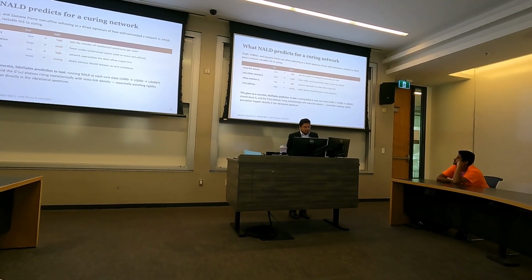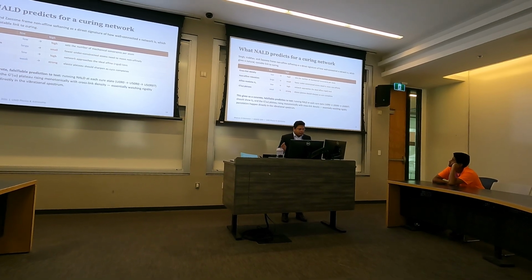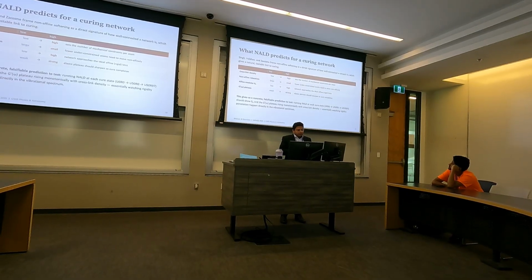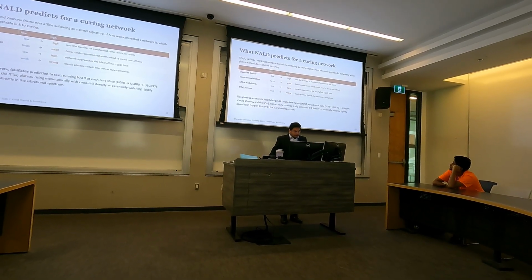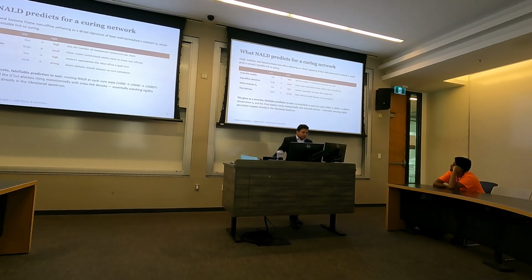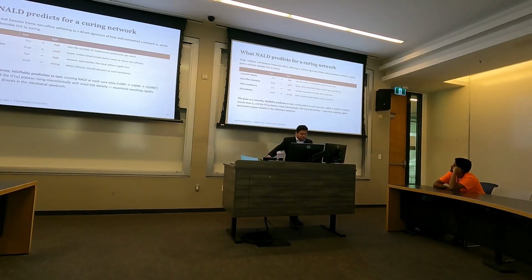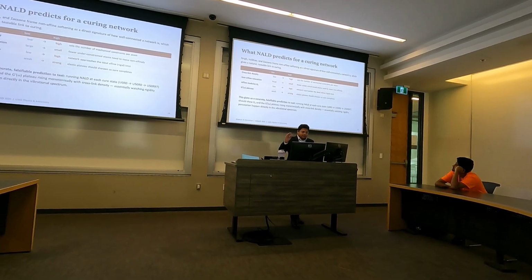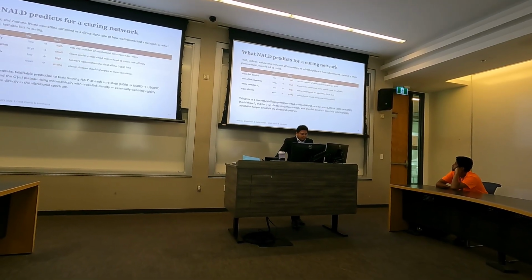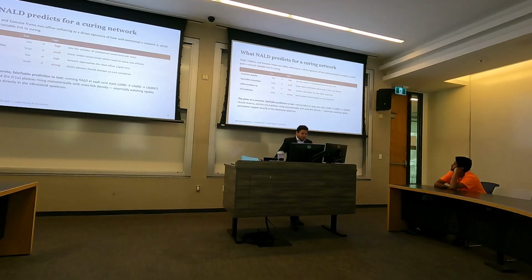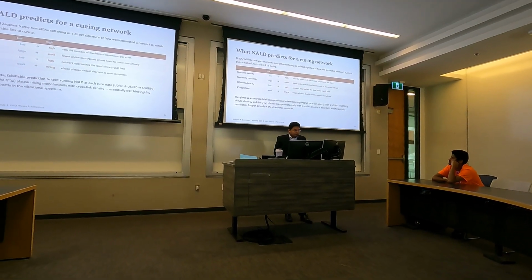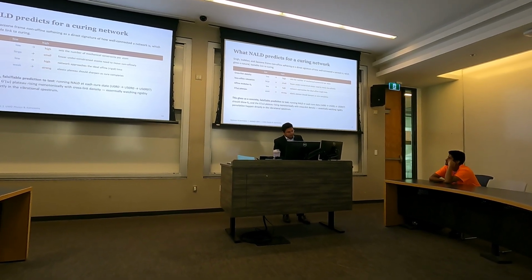This is very interesting, because non-affine softening is a direct signature of how well connected the network is. This is something that you can also get from the graph theory values, but this is a secondary validation that we can get from it. Fewer mechanical constraints per atom means more non-affine motion and a softer material. As the curing proceeds, we see the number of constraints per atom increases, because more cross-linking is happening. And as the theory predicts, the non-affine relaxation should decrease because of that, and the affine modulus should increase, and ultimately the elastic plateau you will be seeing in G prime should sharpen as it strengthens.